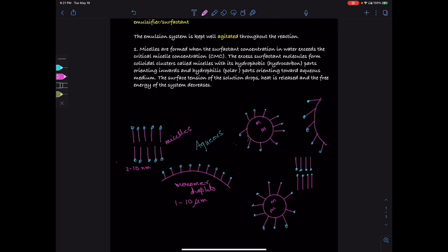So, how does the chain initiation and propagation happen? First, the initiator releases radicals in the aqueous medium. These radicals get into the micelle and trigger the chain propagation. The chain propagation continues as the monomers inside the particle get consumed.